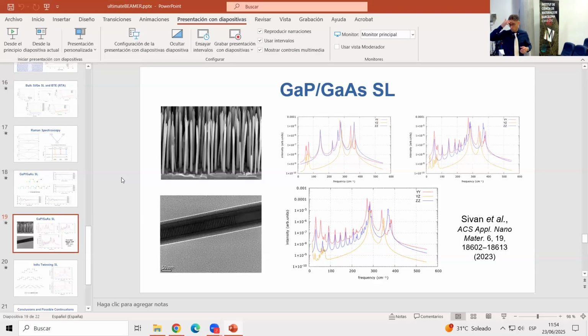I mean, here we are really taking quantum mechanics into account to a very good degree of approximation. Of course, still you need to make some approximation. Physics is all about approximations. Everyone in the field knows this. You can never know if some relativistic effect would kick in. But the ab initio software, which implements quantum mechanics and takes electrons and their quantum nature into account... for example, you cannot predict superconductivity with this formalism, because superconductivity has to do with the phase of the wave function, and you're not keeping track of that here. But it is enough to compute the electro-optical properties.